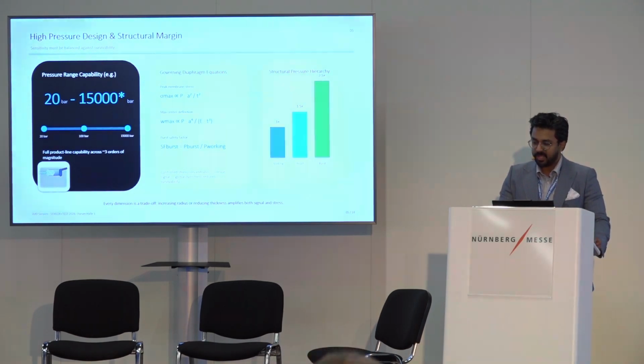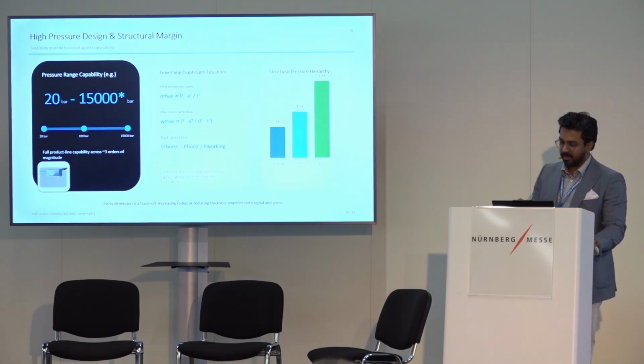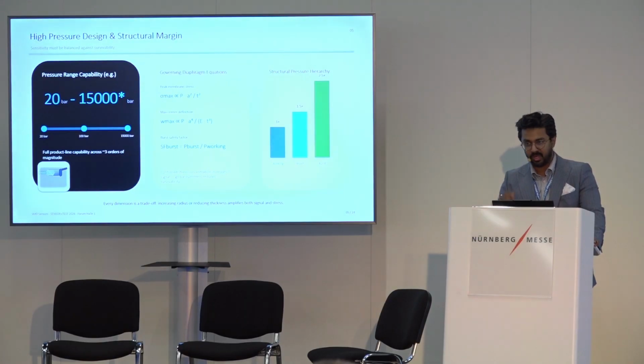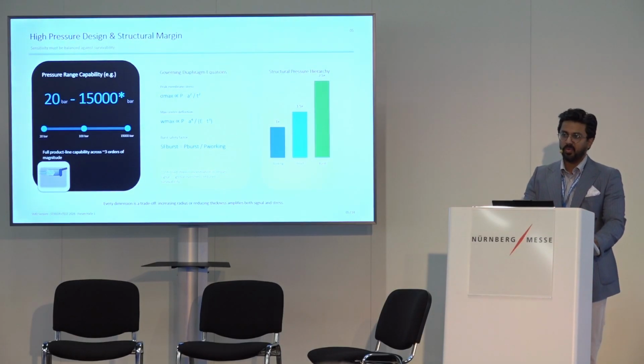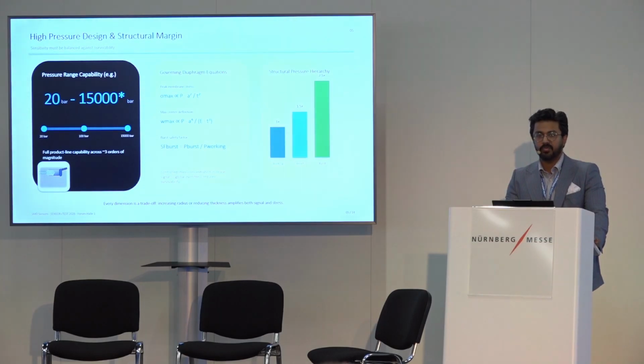And maximum deflection is a bit more dramatic. If you look at the bottom left figure, if you turn the knob a bit on a certain region, you're going to see all this variability. Depending on that, we have to look into the peak membrane stress, the center deflection, and subsequently the burst safety factor as variables when designing, keeping in mind manufacturing. Just by playing around with these ranges, the geometry and the gauge factors, at SMD we can do between 20 bars and 15,000 bars, and these are different range capabilities that we create design factors for, which is super important after we do thin film.